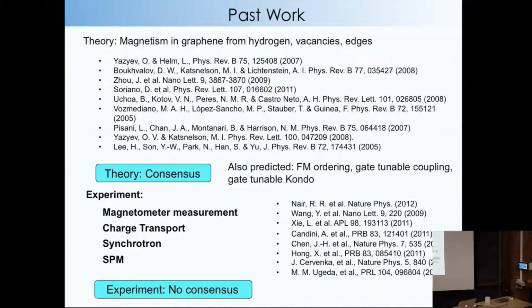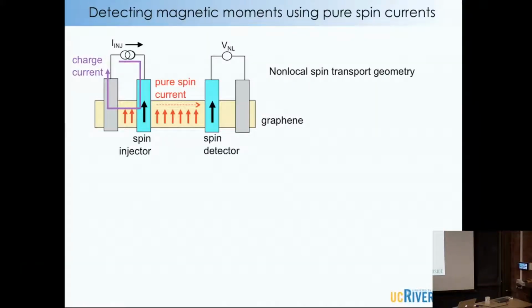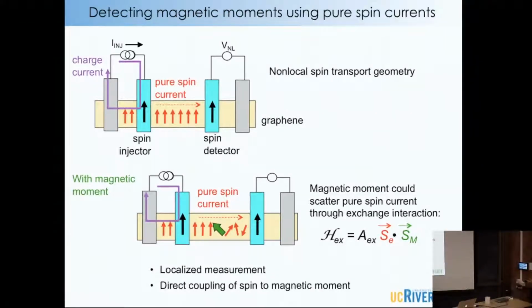And so we really wanted to understand if there indeed are magnetic moments and if you could have magnetic ordering inside graphene. So this is the same kind of experiment I showed you before, but the big difference is I want to put in a magnetic moment, say with hydrogen. If you do that, these electron spins that are moving across here could interact with the fixed magnetic moment, through the exchange interaction that I discussed earlier. What should happen is that this moment should start depolarizing those electron spins, and then the polarization at the detector should go down. So that's the idea.